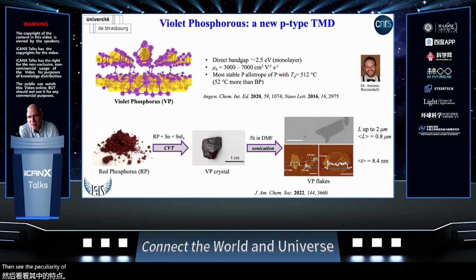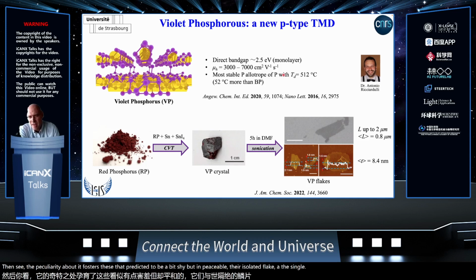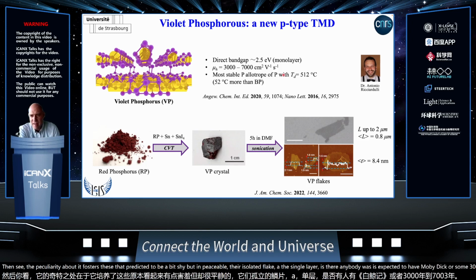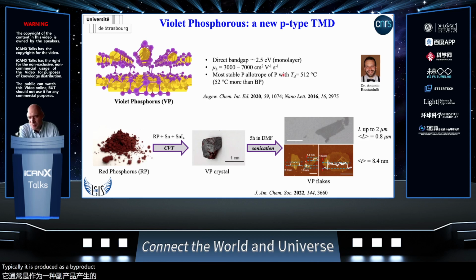the peculiarity of violet phosphorus is that it is predicted to be p-type. In principle, the isolated single-layer flake is theoretically expected to have a mobility from 3,000 to 7,000, so it's pretty high. Typically, it is produced as a byproduct when black phosphorus is produced, but one has to remember that it's much more stable than black phosphorus, and therefore there is a simple way to make it. When you heat it up, you arrive at a certain temperature where the black phosphorus is completely destroyed, and you have a window of 50 degrees in which you can produce pure violet phosphorus.